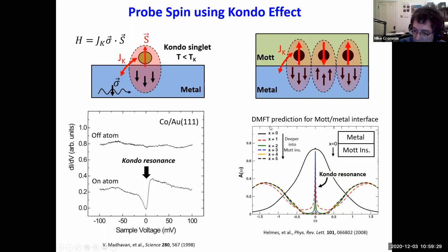So this is a theoretical prediction that was made back in 2008 by Helmes and coworkers, where they actually predicted what happens when a metal is on a Mott insulator. And they predicted basically what I just said to you. Here from the prediction, you can see that if you go into the metal, you get this nice continuous density of states. But as you go into the Mott insulator, you start getting this Kondo peak, which is due to the Kondo effect.